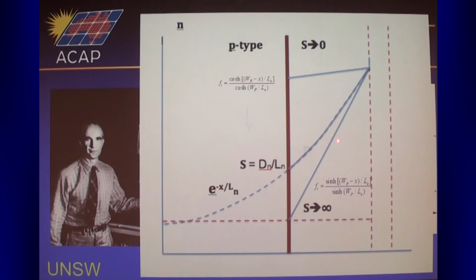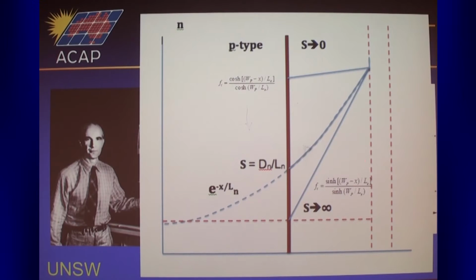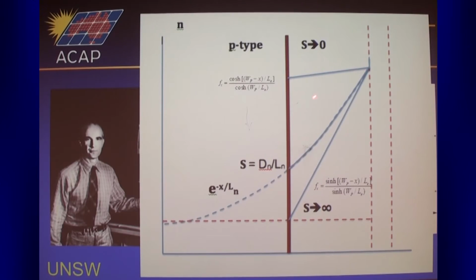So, if you look halfway across here, this will have about half the value that it does at the junction, so that gives you a 50% probability of collection of carriers, which is about right, because this is acting as a sink for carriers. If you short circuit a junction, that means there's no excess carriers there, so that'll act as a sink. So the sink here and the sink here just battle for the carriers, and you have a 50% chance of collection. However, if you do something that's good for the voltage and try and reduce the surface recombination velocity, you can see that you bump up the probability of collection of the carriers as well.